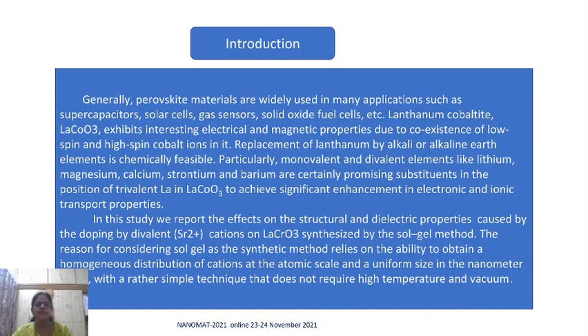In this study, we report the effect on the structural and dielectric properties caused by doping divalent strontium cation on LaCoO3 synthesized by sol-gel method. The reason for considering the sol-gel as the synthesis method relies on the ability to obtain a homogeneous distribution of cations at the atomic scale, and this technique also does not require high temperature and high vacuum.